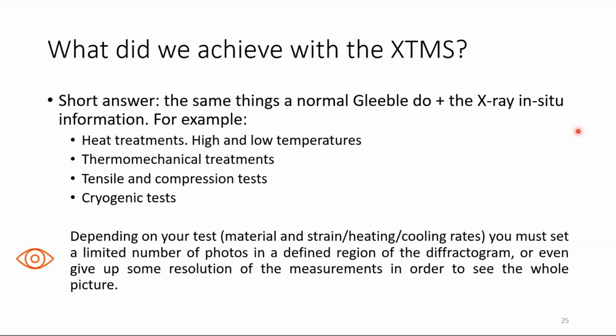There is something that we need to be aware of. Probably other presenters have talked about it. You need to know your material. You need to know how it behaves, where the transformations occur, or where the phases behave in one way or the other. Why? Because you need to match your experiment with the data acquisition of the synchrotron. If you have a very fast phenomenon happening in your material, probably you are not able to see it by X-ray diffraction. So you need to match the rate of your experiment, let's say strain, heating or cooling, with the X-ray acquisition.